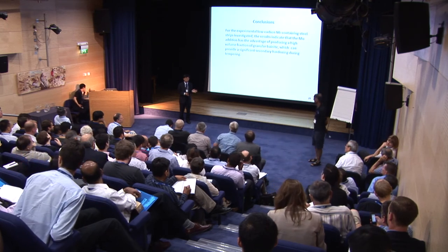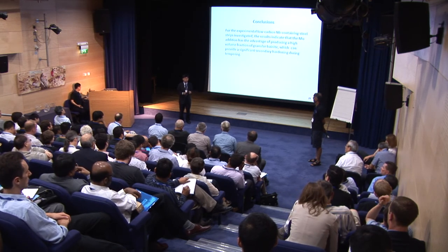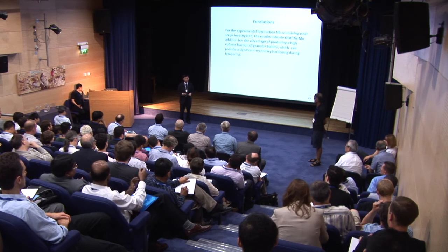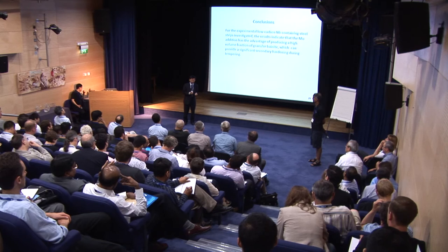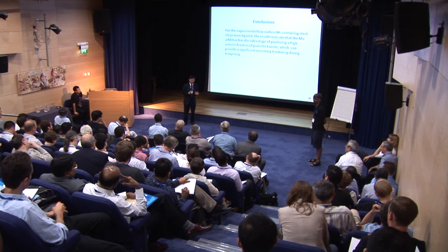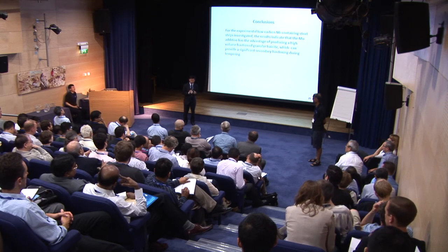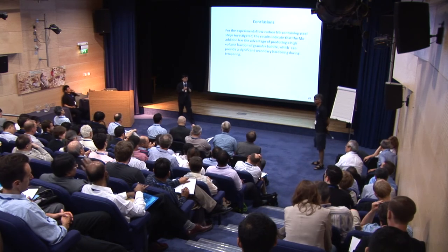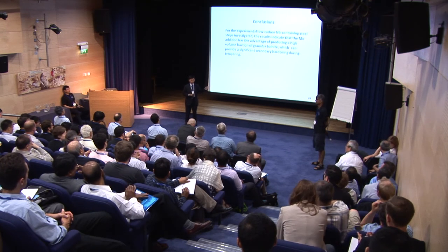For this alloy design, in fact, we should have a high volume fraction of bainite. So how to get a high volume fraction of bainite? I think the niobium and moly play an important role for the hardenability of bainite. So in this work, we add niobium at 0.08%. That's the reason we use niobium instead of vanadium, because we would like to increase the hardenability of bainite. And your second question: because of the time limit, I couldn't show my results for 500 degrees C, 550 and 650, but I chose the best one, 600.